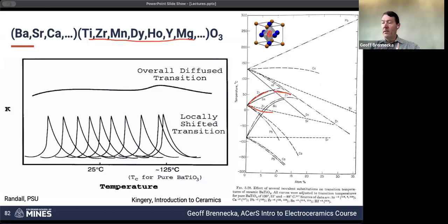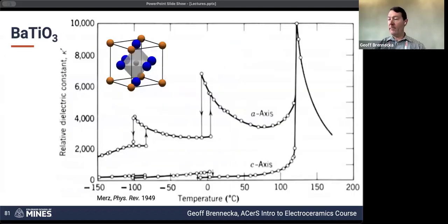We see that the result of B site doping tends to take these phase transitions and shift them toward or away from each other. And so generally doping the B site does what's called pinching. So it has the phase transition series compressed together or spread apart. Whereas generally replacing the A site with something else will cause the entire series to shift one direction or the other, keeping the distances between those relatively similar.